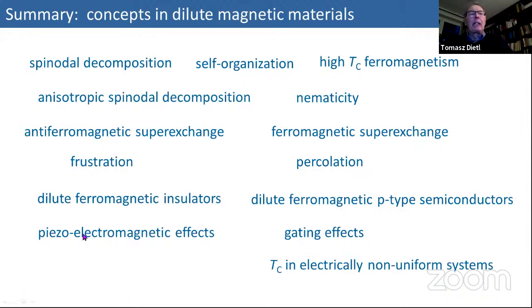Also, I discussed electric field effects in dilute ferromagnetic insulators and dilute ferromagnetic semiconductors, saying that here we have piezoelectromagnetic effects dominating, changing magnetic anisotropy by converse piezoelectric effects, which change the dimensions of the samples under an electric field. And here I discussed gating effects, in particular on TC, in an electrically non-uniform system. Thank you very much for your attention.